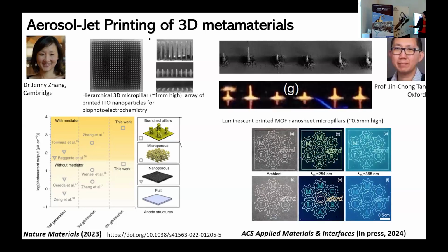Another very recent work, which is about to come out very soon, is work we did with Jin Chong in Oxford, where he works with MOFs, and he uses these MOFs as hosts for luminescent dyes. And what we showed is that you could actually print them. So these are prints of these various MOF structures which are infused with these dyes. And when you look at this under UV, you can see the luminescence. You can do this with various dyes, so yellow, red, green, whatever. And then you can mix them all in different proportions to see different colors. We've even shown in this paper that you can get white light emission from this.